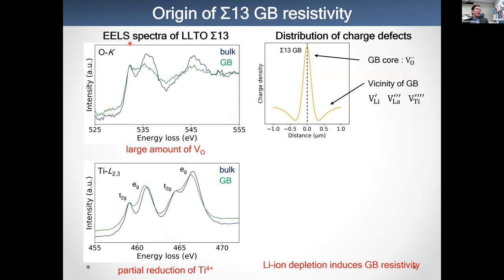Again, as I told you, from this oxygen K-edge profile, this indicates that a large amount of oxygen vacancy is introduced. And this titanium L3 chemical shift indicates that titanium 3+ is partially included. And the distribution of charge defects is in this way. In the core regions, the oxygen vacancy is increased. And in this negatively charged region, what are the main vacancies?